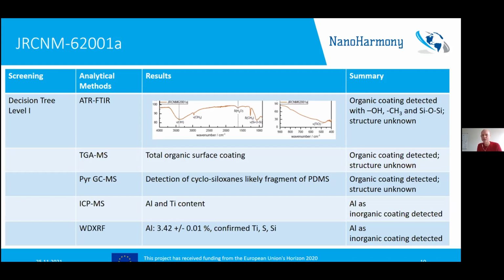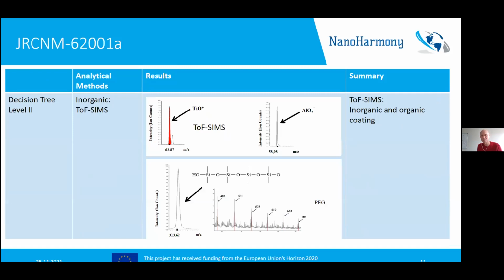ICP-MS and XRF could both screen and identify aluminum as the inorganic coating, but these techniques could actually also quantify it. And pyrolysis GCMS could also identify the organic polymer. This was also possible with TOF-SIMS, which could actually reveal both inorganic and organic coatings in this sense. But it's important to mention that these techniques were perfect for some compounds and useless for others, and vice versa.